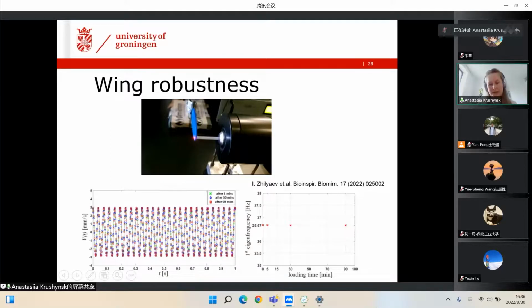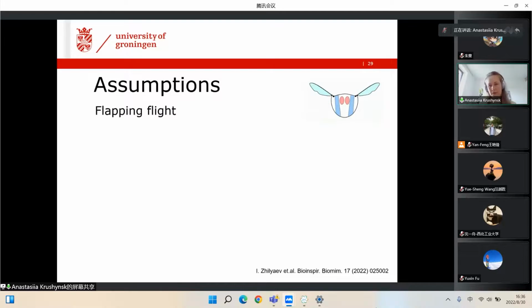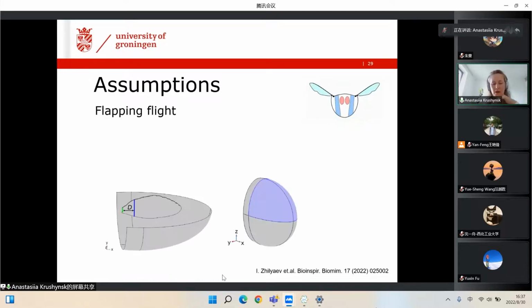Okay, being excited by these results, we wanted to model the wing dynamics. And for that, we chose flapping flight because it's much easier to model. For that, we put our wing model in the half ellipse, which represents air, fixed the base, and applied a sinusoidal loading at the bottom surface of the wing. In this way, we can reproduce these dynamics, as you can see in this animation on the right-hand side.